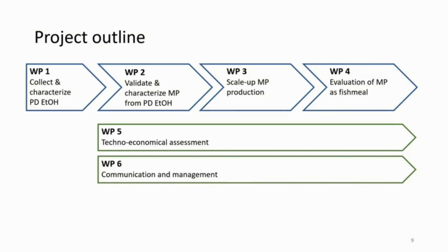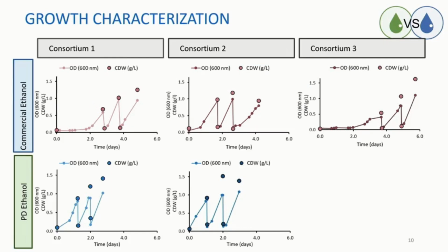So in the SEMPA project, we did the typical things that you do when you have a new development. We characterized what this pre-distilled ethanol, this direct ethanol produced from microorganisms, is like in terms of composition. We created consortia of microorganisms to grow on it. We scaled it up with Biobase, and then we evaluated its use as fish meal, both for salmon and for prawns. So I will not dwell too much on the details of the research, but this is more or less a kind of proof that you can grow microorganisms on this ethanol you make from the blast furnace gas as well as you do on a commercial ethanol.